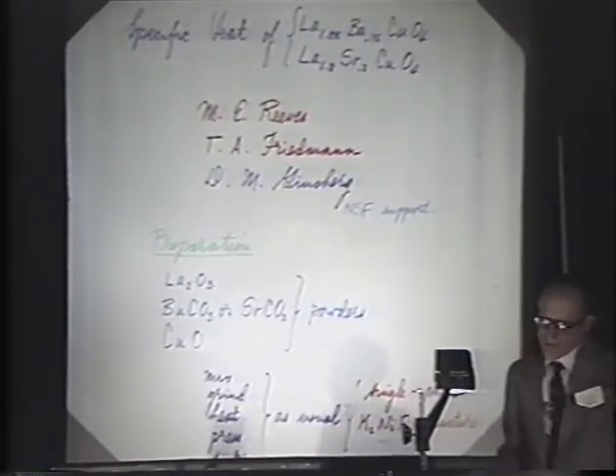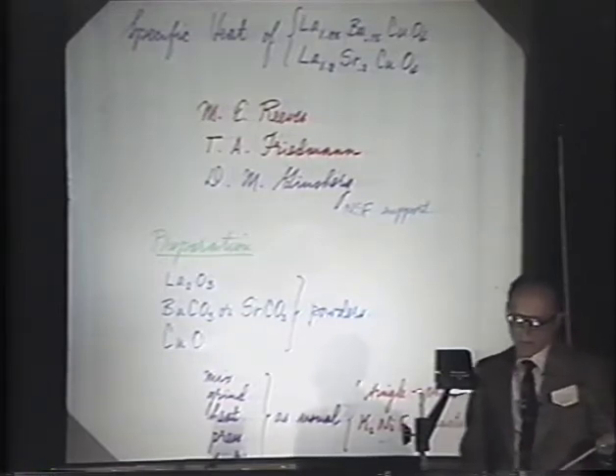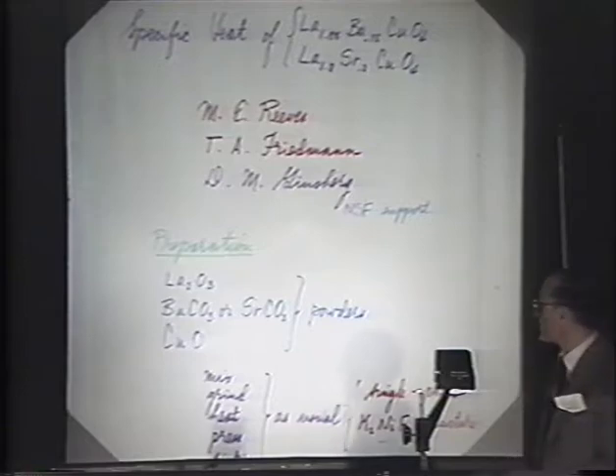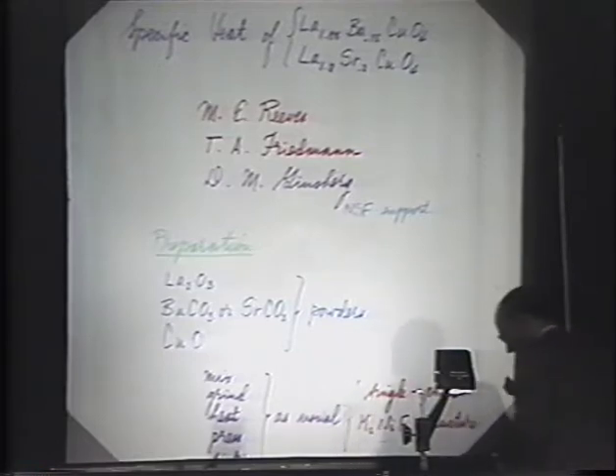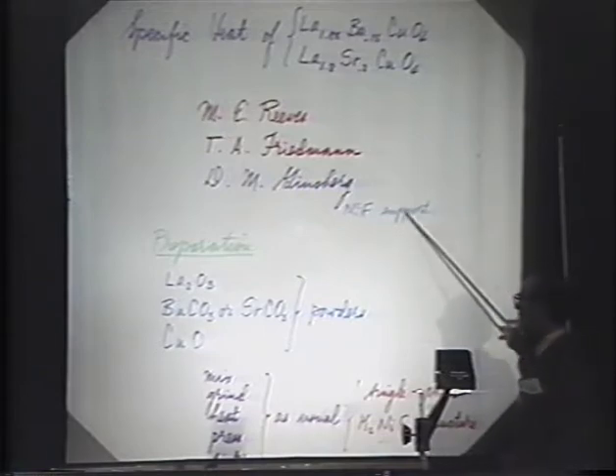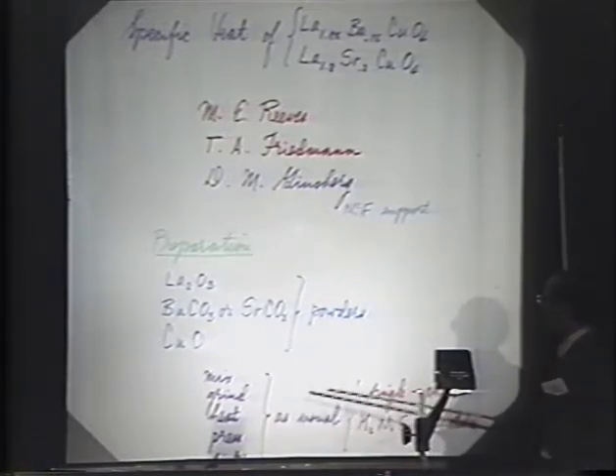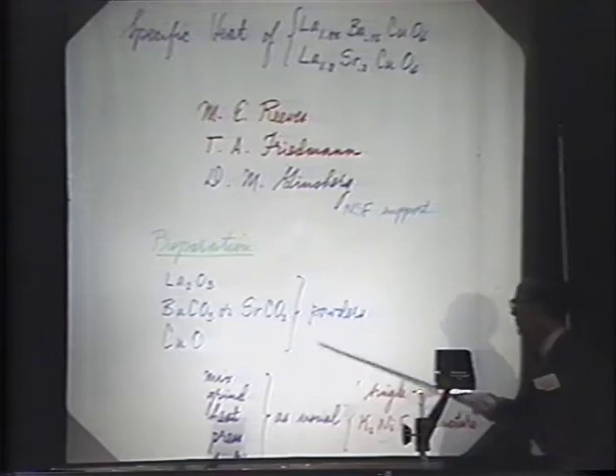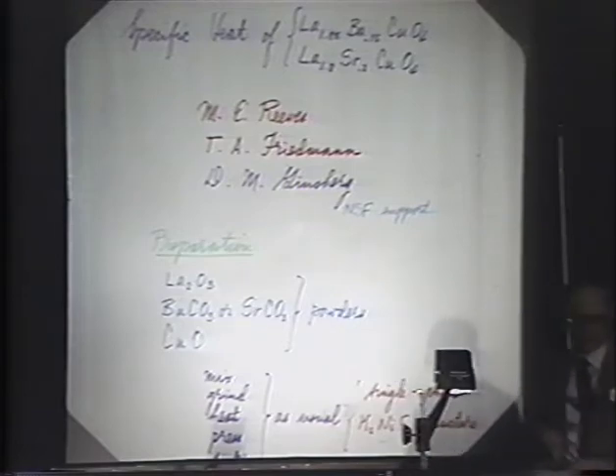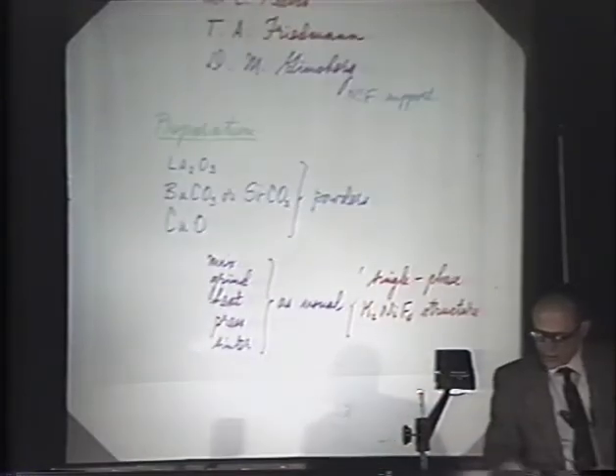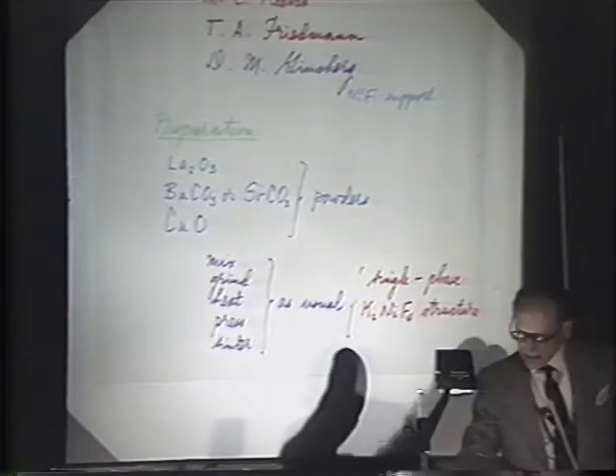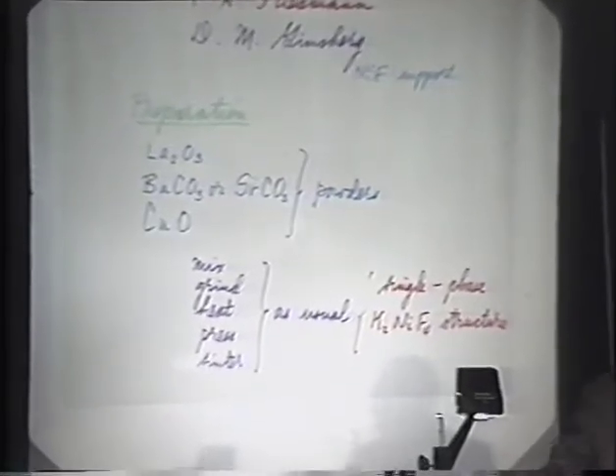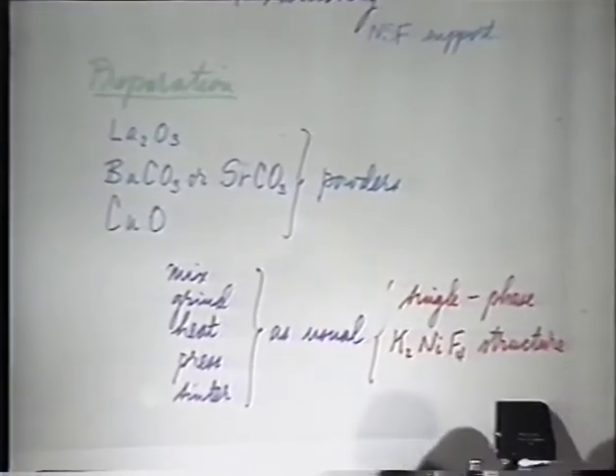I'm going to talk about the specific heat of the lanthanum barium copper oxide and lanthanum strontium copper oxide. The two students who did the work are Reeves and Friedman. We have NSF support, for which we are very grateful. We prepared the samples in the usual way using carbonate and oxide powders with the usual mixing, grinding, heating, pressing, sintering, and so on. We've got X-ray diffraction data which show that we have single-phase samples with the K2NiF4 structure.